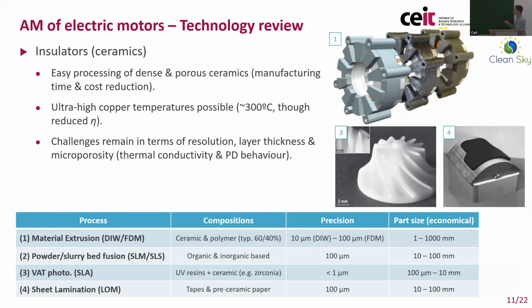For instance, in this picture, this was a study made by a university in which an axial flux motor was totally additively manufactured, in the sense that the iron parts, the copper, and a ceramic insulator were all additively manufactured. In this case, this allowed the machine to operate up to 300 degrees, although with a reduced efficiency due to the high current density obtained in the copper coils.